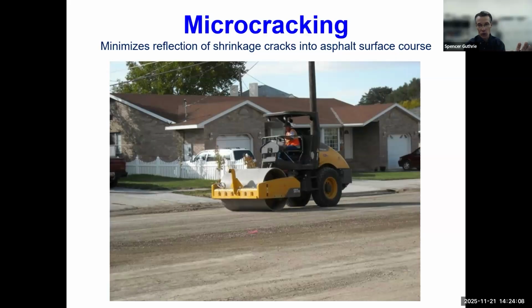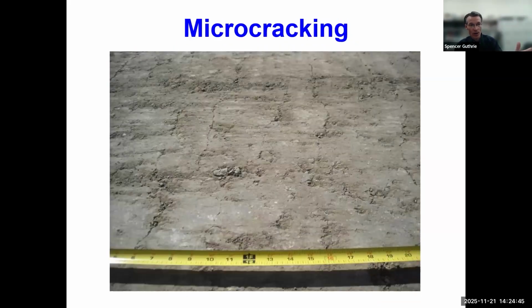But the idea is that just 2 or 3 or maybe 4 days after construction, during the curing process, we bring the same smooth drum roller to the job site, and now we turn on the amplitude of vibration, so it's maximum, and we have the roller operator drive up and down the grade several times where we're monitoring the stiffness after each pass, and we are cracking deliberately the full depth of the cement treated layer. In other words, when we're finished, we have a series of very fine cracks that look something like this that allow for the shrinkage to occur, the total shrinkage, over all of these hundreds or thousands of tiny cracks, such that no crack ever develops a sufficient width to propagate into the overlying asphalt.